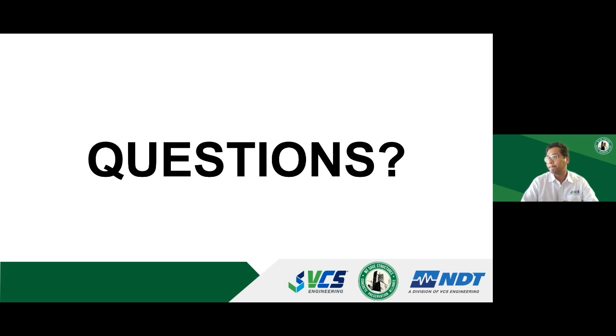Okay. Natalia, you would like to add anything? Yes, thank you. I'd like to add to that. We all know that structures up north suffer from de-icing salt deterioration in the decks. So if the owner is planning a significant investment in the structure to rehabilitate the deck and any other areas that are affected by chloride-induced corrosion of the conventionally reinforced elements, it would be a good idea to at least do some testing to verify that there are no issues with the PT, which is typically in the girder webs, because the testing would be rather small compared to the budget of the rehabilitation, and it would be worthwhile to confirm that there's no additional interventions needed or that there's no additional concerns with the PT that might change the rehabilitation approach. Right. Okay. Thank you, guys.